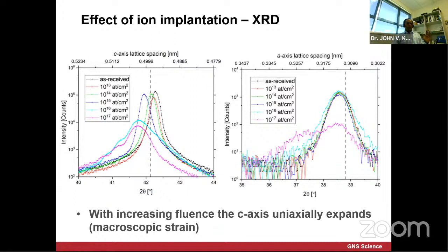Because you see there is no change in the A-axis strain up to 10^16. And you're starting to see the broadening, we call it microstrain. Then when you go to 10^17, there is a macrostrain, because there's a big shift. If you look at the right-hand side, which is the A-axis, and the left-hand side, the C-axis, the A-axis is not a big shift until you go to 10^17, where you are basically making it amorphous. But if you do a tiny fluence like 10^13, 14, 15, 16, the A-axis lattice doesn't change much, but the C-axis changes a lot. So we looked at it more closely again to understand the strain level.